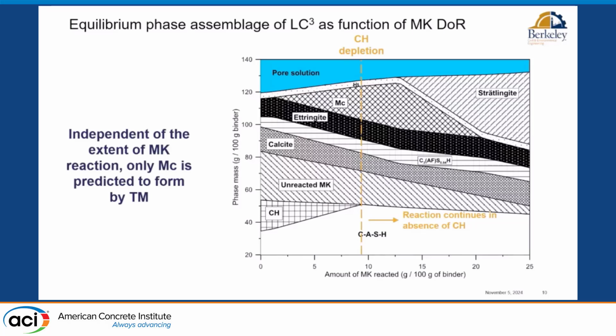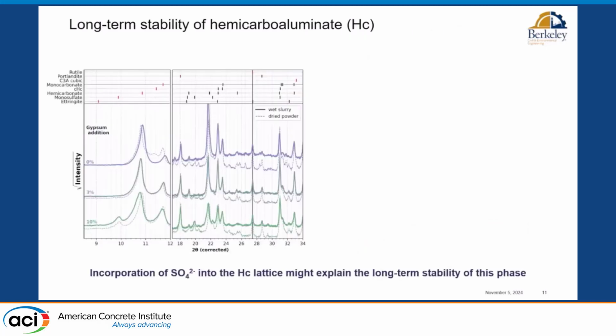And the reason for that is that in the database, the monocarboaluminate that was used to obtain the thermodynamic data is pure or synthetic monocarboaluminate. And we went a little bit deeper to try to see if that was the case of the phase that we actually have in LC3 cement, and we did that by producing synthetic carboaluminates from hydration of pure C3A, and we added certain amounts of gypsum to the system. And what we see is that the more gypsum you add, you start forming monosulfate in combination with carboaluminates, but not always. And this is the interesting part.